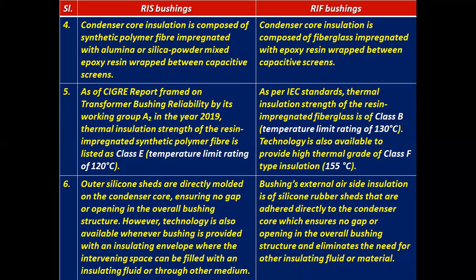But for RIF bushings, as per IEC standards, the thermal insulation strength of the resin impregnated fiberglass is class B type insulation, that is, a temperature limit rating of 130 degrees centigrade. Technology is also available to provide a higher thermal grade of class F type insulation, 155 degrees centigrade.